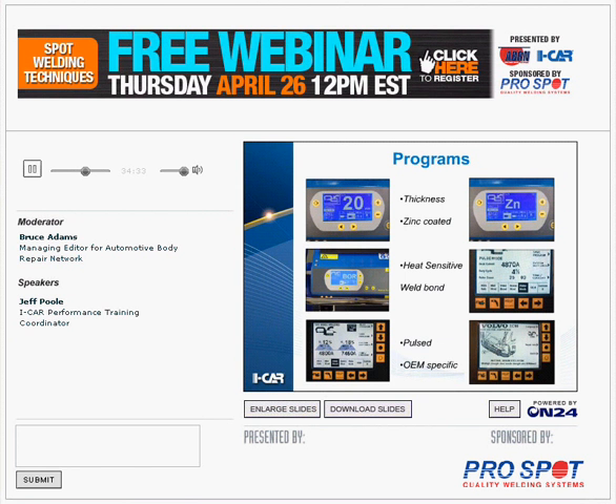Additionally, we may have weld bond settings. The weld bond settings can help account for adhesive between the mating surfaces, and we're going to go into more detail about this a little bit later on, but again, this is typically a two-step weld process. The first step is a preheat, and that burns through the adhesive. Additional settings may include a pulse setting or a soft start that may help to burn off any impurities in the weld zone. I'm really hopeful that the panels have been prepped properly and that we don't have impurities in there, but again, this is something that may be available on the equipment.